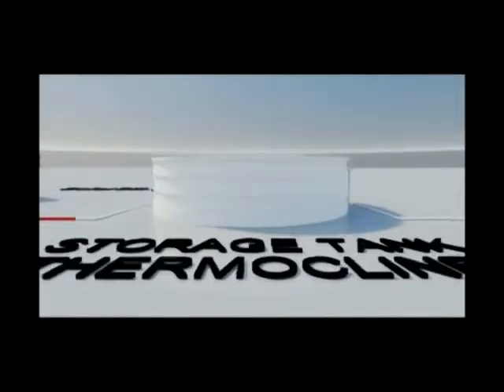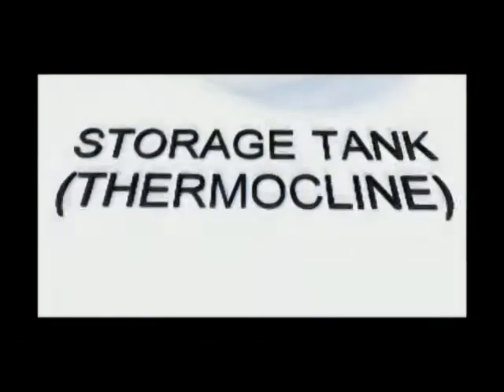Using the example of titanium, the complexity of the ECO-X process over that of the complexity of Kroll is clear to see. With about 3 volts of electricity used for the electrochemical process at elevated temperatures, the bulk of the energy exiting the ECO-X process is recycled and kept in a thermal energy storage unit. With molten salt giving up less than 1% of its energy over 24 hours in a well-insulated tank, the excess energy after running the ECO-X process is used to generate electricity at times where demand is highest to help recover capital and plant operating costs.